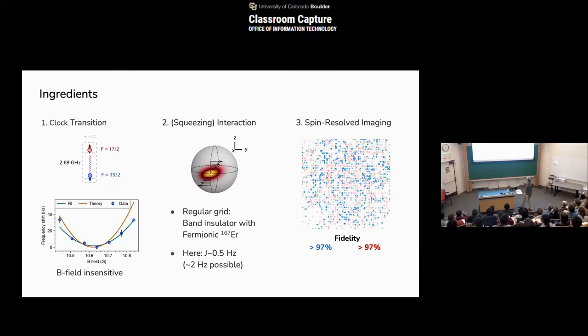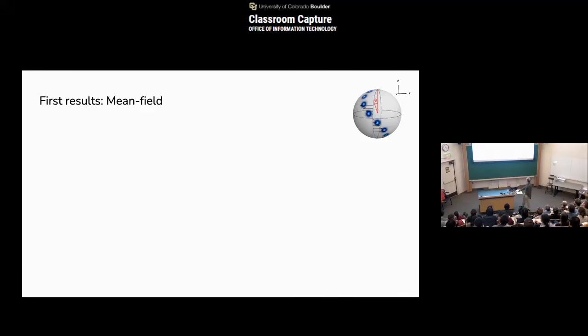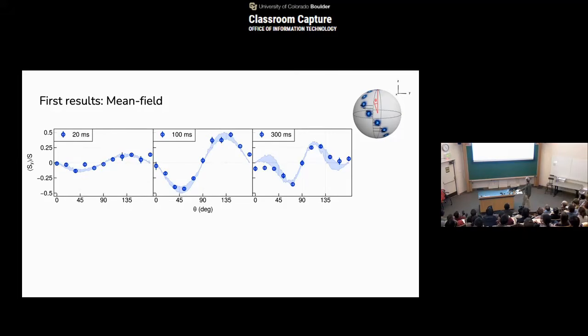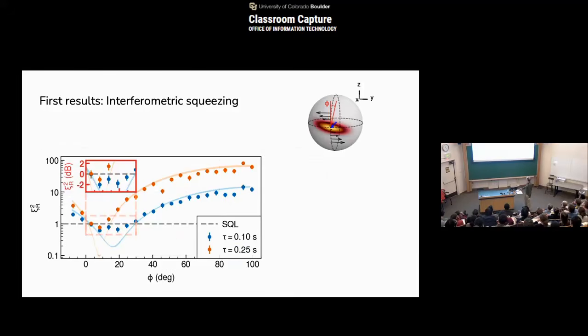And then we do the squeezing, and we need to read out, of course, with very high fidelity. Actually, by now, the fidelity is much higher. It's 99.8 as of last week. And so we are trying to see the spin. The first thing is we just prepare a spin on this big Bloch vector. Depending on the angle, we can see how it now precesses, because the squeezing is caused by some shearing motion. So we can map out this shearing motion here. So that works exactly as expected.